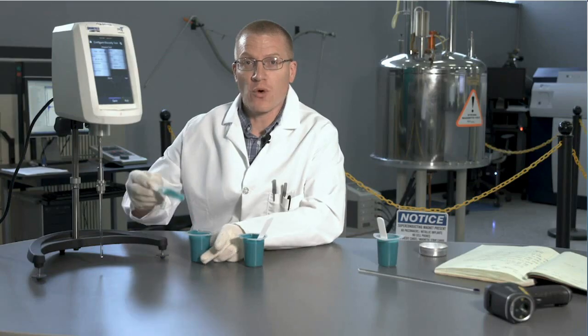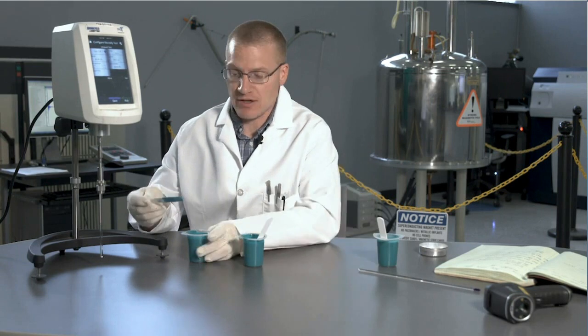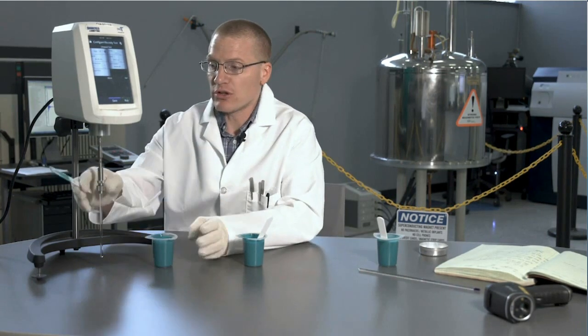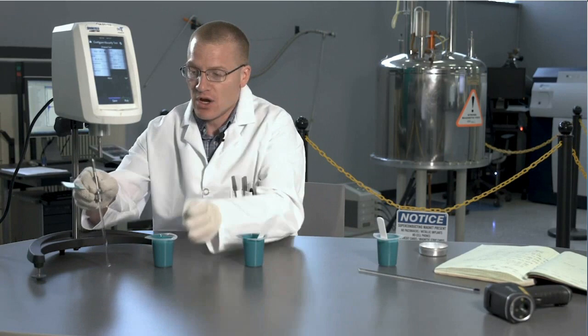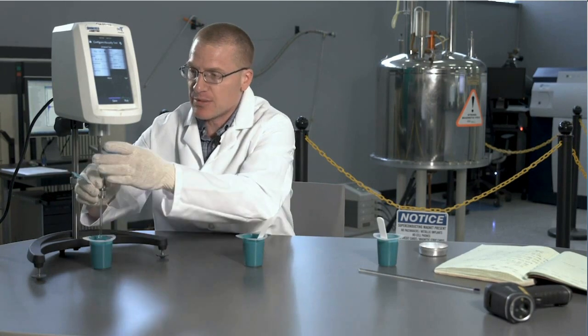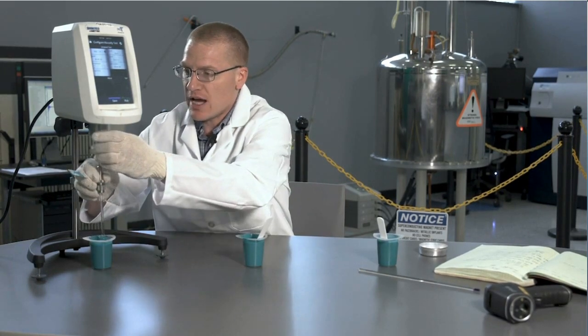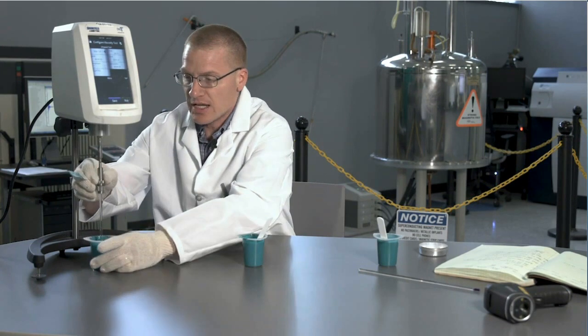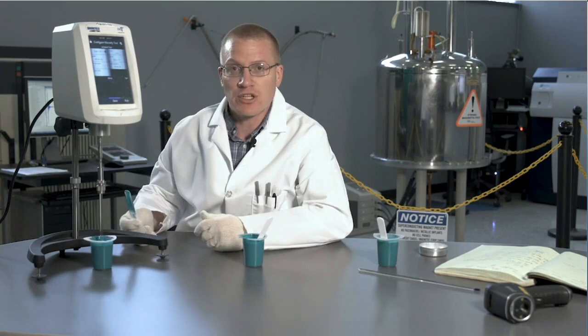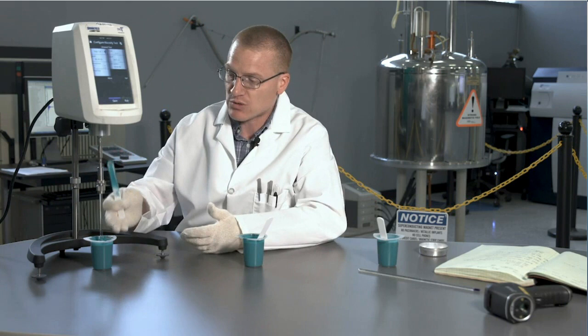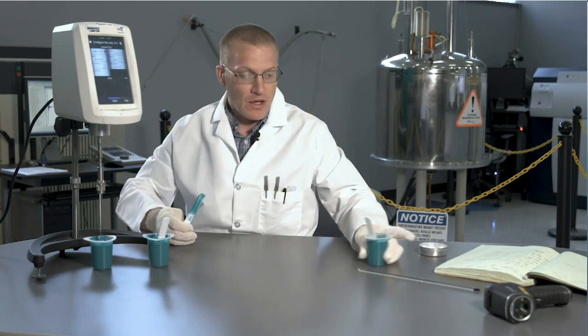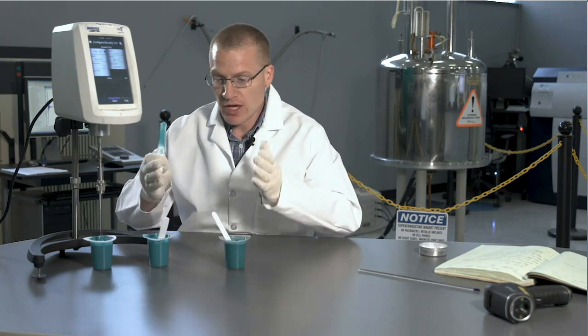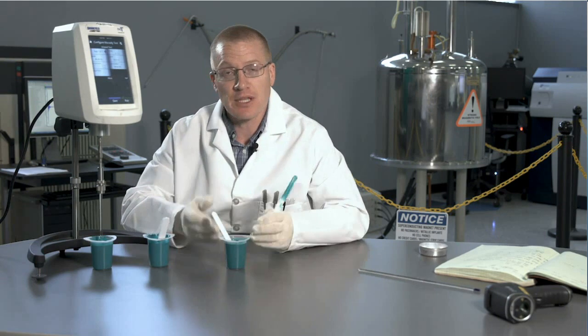So we're demoing gel time versus pot life. And in this example, we're going to show you how gel time is a very specific test where we actually measure the viscosity of the material over time as the material begins to react. And this would be what we would call our gel time apparatus, where we have a glass rod that's measuring that gel time. We're also going to be comparing that to the same chemistry of product, but something that has more of a pot life.